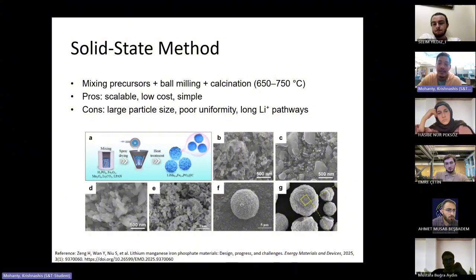So 650 to 750 degrees Celsius is the temperature that most of the methods try to reach with the material itself. There have been several papers which have focused on the importance of temperature in LMFP, and all the papers state that 650 to 750 is the right temperature for synthesis. Again, it is scalable, low cost, and simple. The cons are that we cannot determine the particle size because we are just grinding it. At the end of the day, there is no filtration or homogeneity in particle size, so there are poorly uniform particles. And because particle sizes are larger, lithium pathways will be longer because they do not have anything to penetrate through.